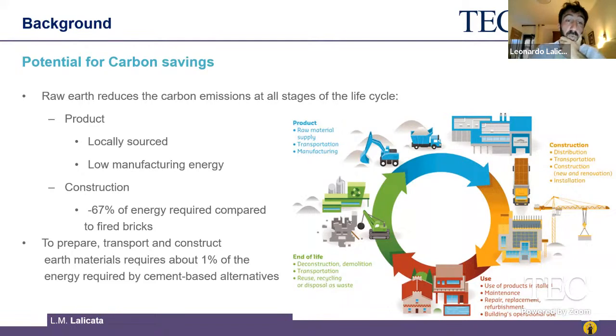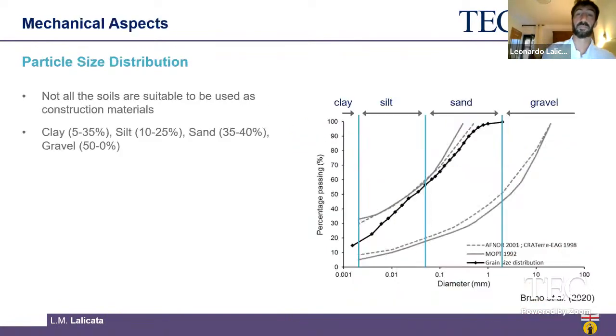And if you compare that to the energy required to build the same structure using cement-based alternatives, you find that you need approximately 1% of the energy compared to the cement alternative. Which again is a massive decrease and of massive importance for carbon savings in this regard. But first of all,